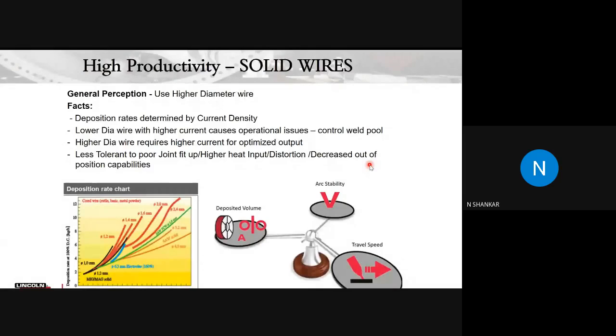But Lincoln normally looks at what is the most cost-effective way of depositing more. Now I want to address the general perception that people have. It is true that when you're depositing using a 1 mm wire and a 1.2 mm wire, your 1.2 mm wire will deposit more. It is not true always. So it is not just decided by the wire diameter. The deposition rate depends on various factors. It's a kind of stability you have to bring. You should have a stable arc. You should have a consistent, more or less stable travel speed and stable wire feed speed.